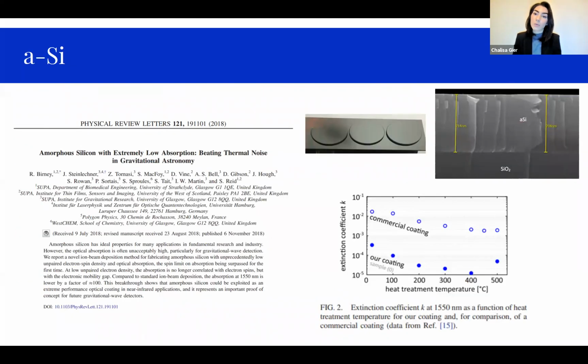As mentioned earlier, with our ECR ion beam deposition system, we have a world record for fabrication of the lowest absorption of amorphous silicon thin films, which is less than 20 ppm absorption at 1550 nanometers. And again, you can find this in the PRL journal published in 2018. And from this, we have found that our coating has a lower loss at 1550 nanometers than the commercial coatings, as deposited as well as post-deposition annealing, as shown here.